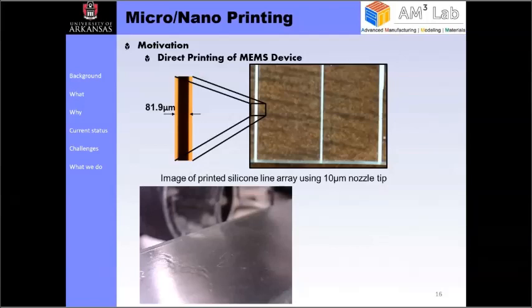We're still having some issues getting the printing line width to conform with the nozzle size. This is a print test of a line with a 10 micron nozzle tip. As you can see, we get about 80 micron line width, which is still not ideal because of some issues that we're experiencing. But one thing that we do get is the thickness. The thickness of a printed line is about 200 nanometers, which we printed using silicone. And the surface roughness of the silicone is about 40 nanometers. We did an AFM scan. I forgot to include a picture here.